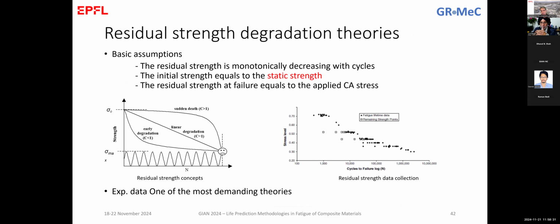These theories are based on the measurement of the strength of the material after specific numbers of cycles, so during the fatigue life. You can imagine that this is a very intensive experimental program, because you have to start testing a specimen, stop the testing before the specimen fails, and do a static strength test. And then at the same stress level, you have to go back, take another specimen, do the same, and again collect remaining strength points. If you do it like that, you have a curve like this that tells you the degradation of the specimen strength after being loaded at a certain level for a specific number of cycles.